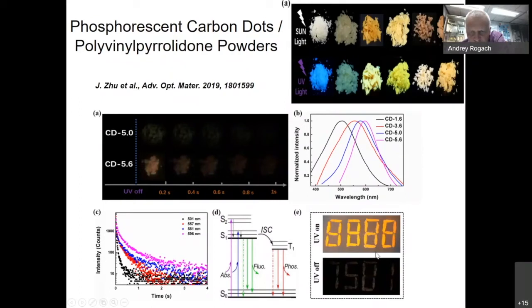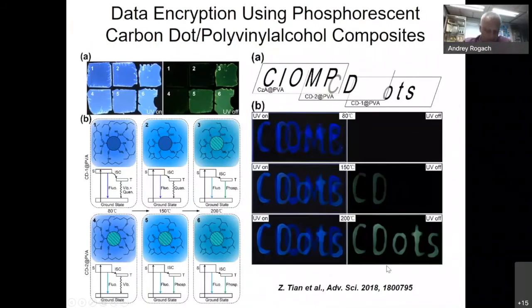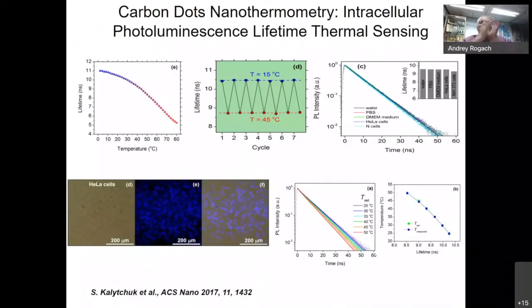So when we, for example, illuminate these materials, what you see here, under illumination, they will emit light, orange light in this example, but even with UV light off, they will still emit color of light. And here, actually, we can encode it with some other symbols, not just 8888, but what is written here, 1501. And this gives us the base of so-called data encryption using phosphorescence composites of this material. Another interesting property of carbon dots is that the emission intensity depends on temperature, and this can be used for so-called nanothermometry.